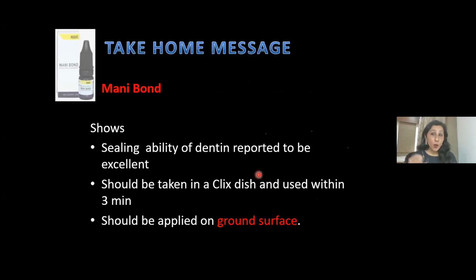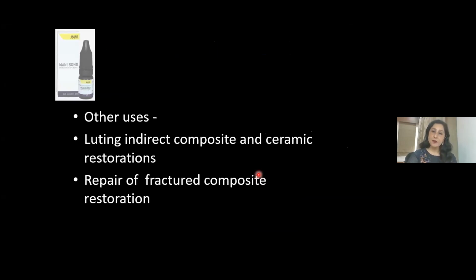So a few more take-home messages for you when you apply bonding agent. Sealing ability of dentine is reported to be excellent with Mani Bond. It can be taken in a Clix dish and used within 3 minutes. So this working time is really a good working time. And I told you self-etch adhesives are to be applied only on ground surface, not on uncut surface, so that the surface energy increases, so that the retention increases, so that the longevity of the restoration also increases.